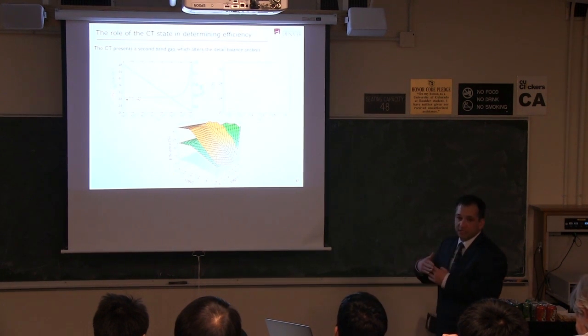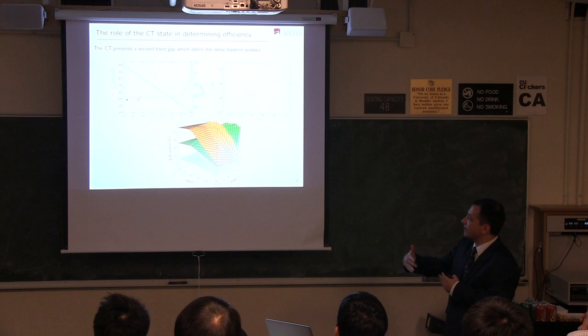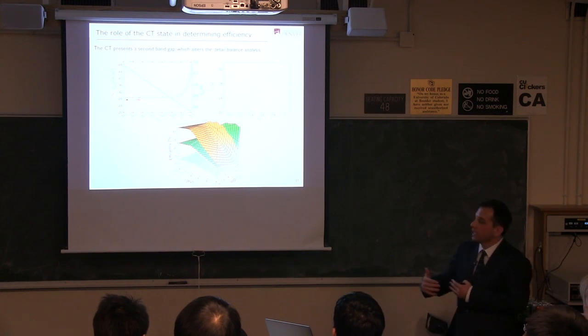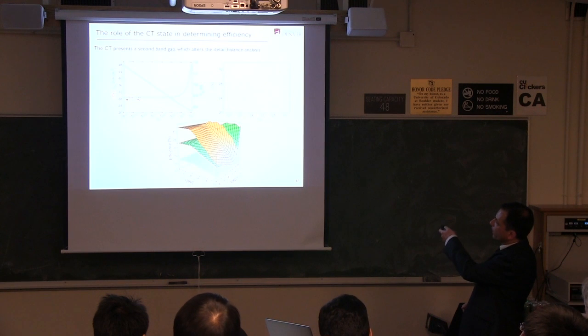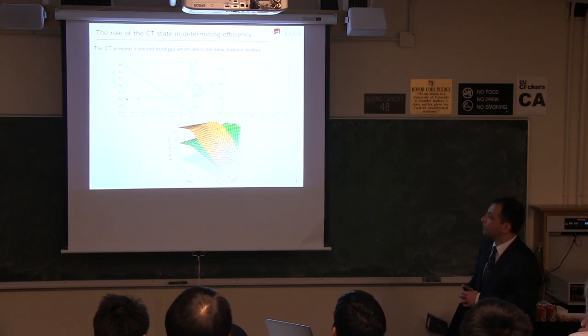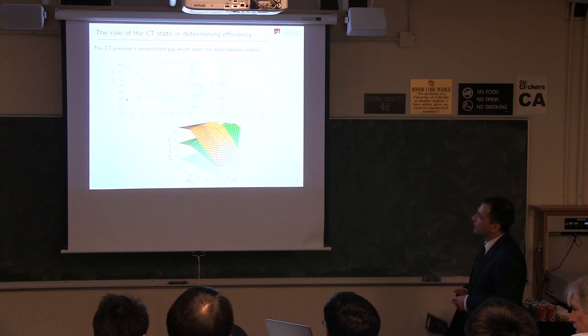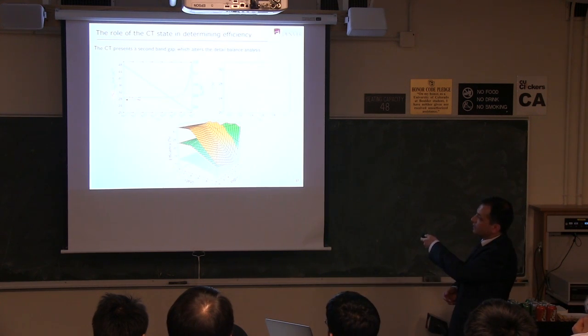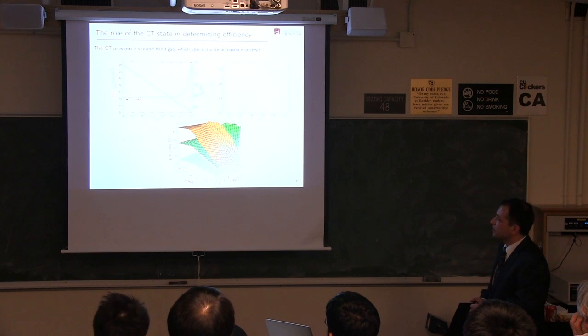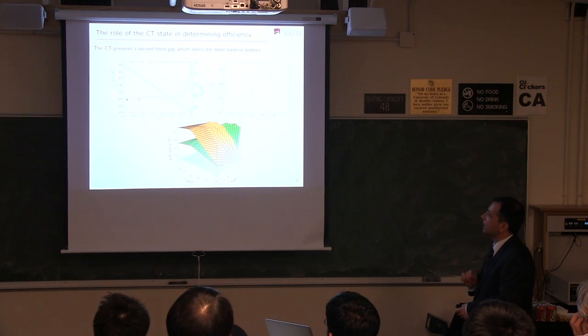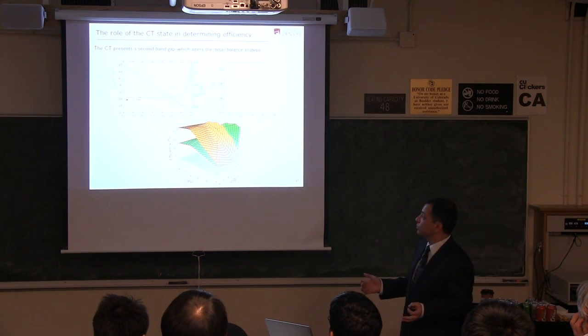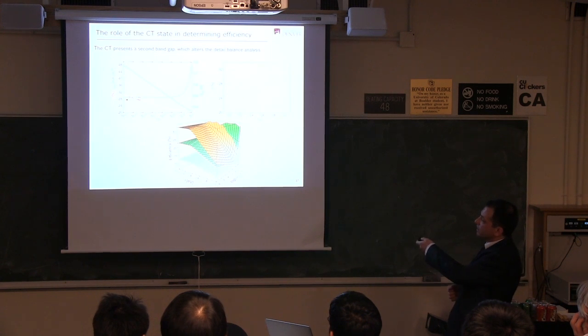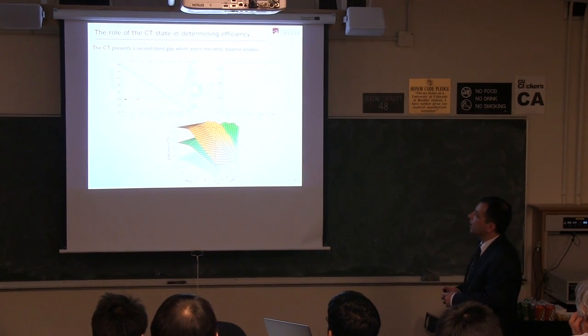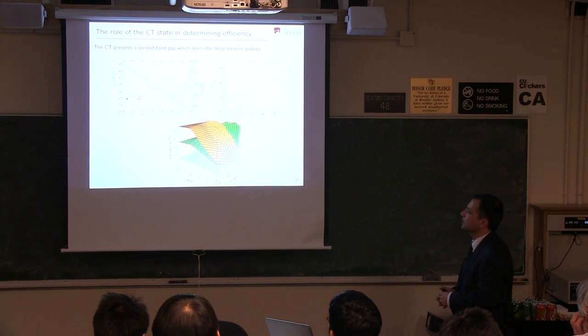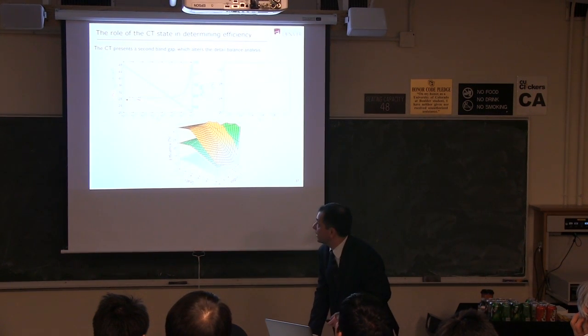But at some point, alpha CT could get so strong that it starts to look like effectively the band gap of the material. And if it was all the way up there, it would mean you have a single band gap material. So you get back to the single band gap limit. The problem is that we currently tend to sit right there at the minimum of these devices. So we have a very weak alpha CT state, which we can't get rid of and we can't make much stronger. We are attempting to do both. Through nanophotonics, we can think about increasing the absorption of that state, which tends to be very weak. Or through some chemistry, we can think about weakening that state. So I'm going to talk about the weakening part right now.